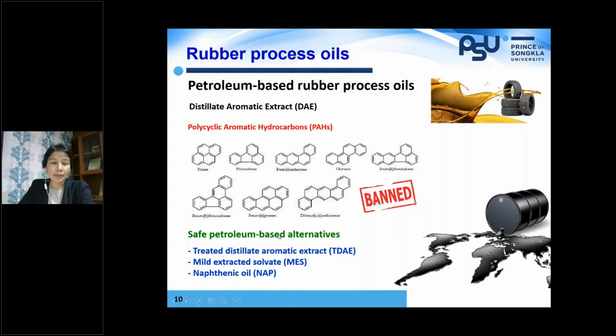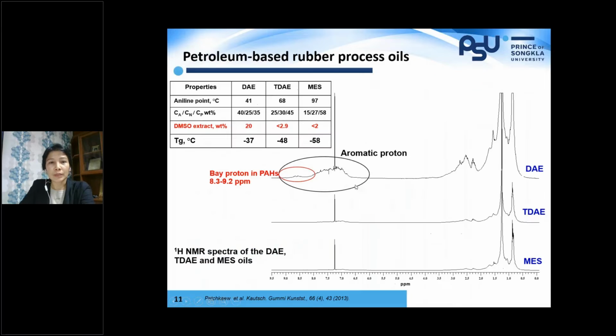But there are different kinds of oil that you can use in replacement of DAE. The widely used replacement oil for DAE is TDAE, so we have treated distillate aromatic extract. We simply do the distillation to remove this PAH out of DAE. But you can also use naphthenic oil or mild extracted solvate. So there are alternatives from petroleum-based oil for this highly aromatic one.